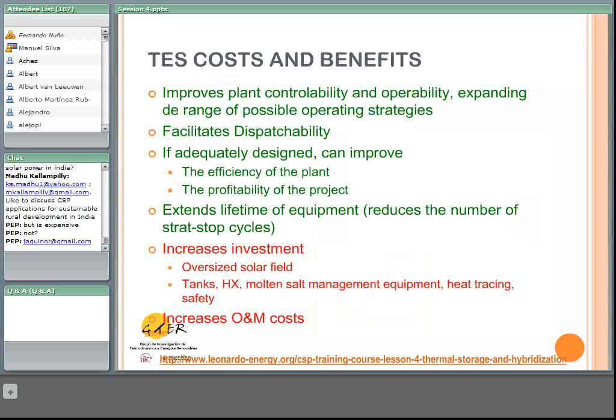On the cost side, of course, a thermal storage increases the investment, because we need not only the thermal energy system, but the solar field has to be also oversized to take advantage of it. For example, for a 50 megawatt parabolic trough plant, normally the size of the solar field is about double the size that would be needed to operate the turbine at full load at the design point. It's a bit complicated, but roughly we have an almost double-size solar field with a 7.5 hour thermal storage system. And on the other hand, the operation and maintenance cost may be increased a little bit by the operation of the thermal energy storage system.